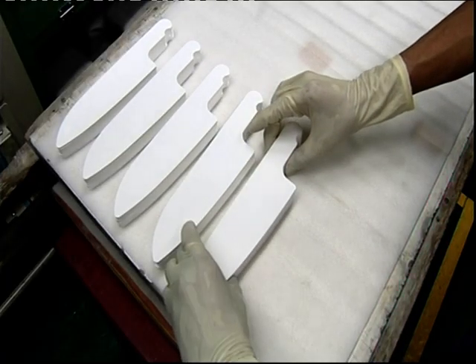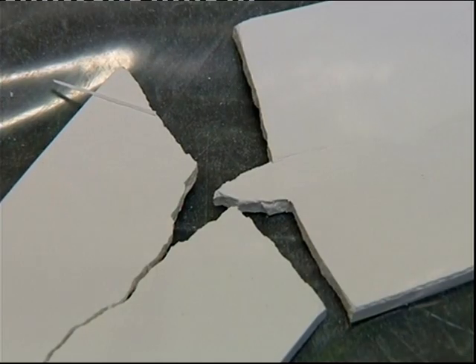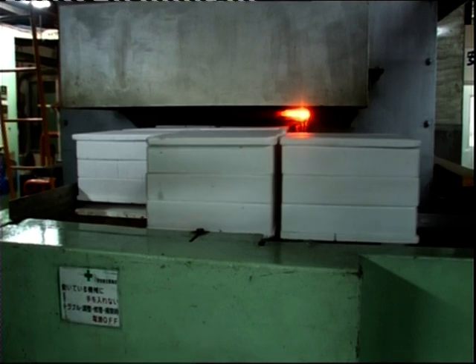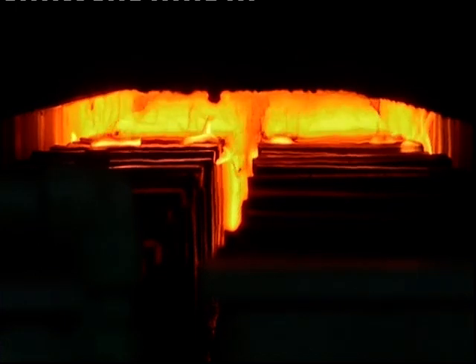These blanks are extremely fragile and can be shattered by the slightest knock. So, like all ceramics, they must be hardened by firing. The temperature inside this kiln reaches 1400 degrees Celsius, and after 48 hours of fierce baking, the soft-powder blanks are transformed into virtually unbreakable ceramic.